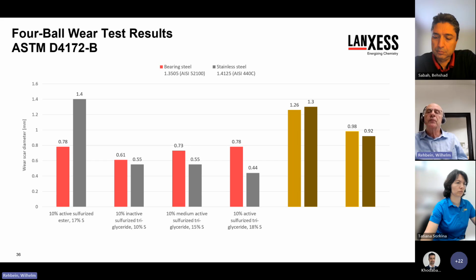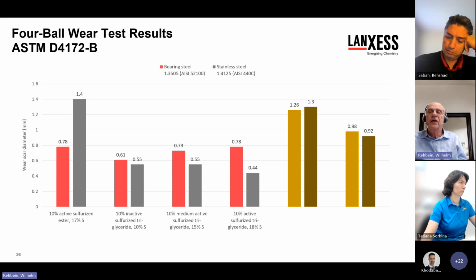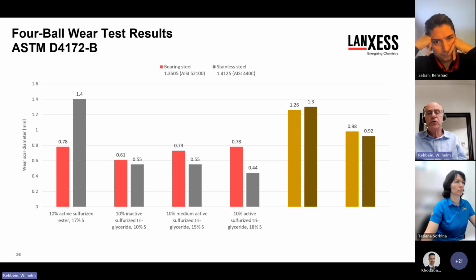And when the test was done using ASTM D4172 parameters, the active sulfurized ester showed high wear on stainless steel balls, probably due to its lower lubricity properties, but the sulfurized triglycerides again showed very low wear on bearing steel and also on stainless steel, particularly again when compared to 10 or 20% chlorinated paraffin containing formulations.